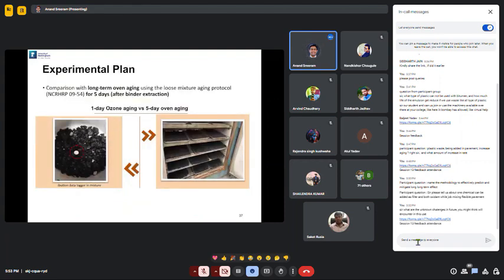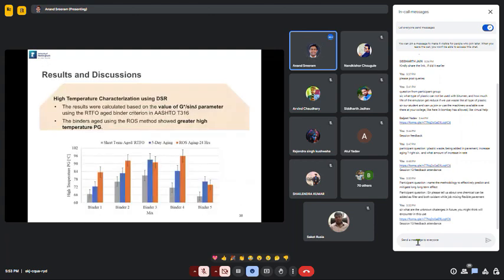So how did we compare the effectiveness of this approach? We did 1 day of what we call ozone aging, and we compared it to the 5-day oven aging, which is what is traditionally done. We compared its effectiveness in terms of meeting different rheological as well as chemical parameters. So we aged our samples in the ozone for 1 day, and we aged some samples in the oven for 5 days.